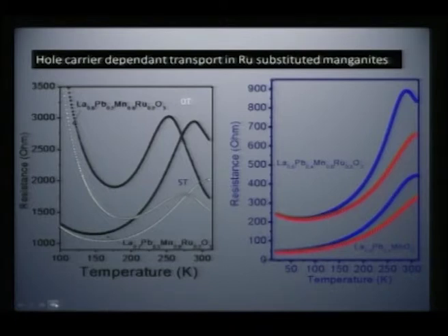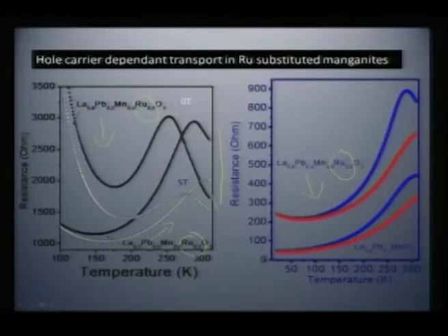We can also try to verify that by keeping ruthenium 0.2 constant in all these cases, and we can try to vary the lead concentration, 0.2 in this case, 0.3 in this case, 0.4 in this case. You can clearly see there is a change in the metal insulator transition, but nevertheless they are still ferromagnetic and they are showing a metal insulator transition. And if you also look at the fall of resistance, say for 0.2 and 0.3, there is a huge fall in the resistance for both these compositions. So what is happening is there is an unusual correlation between manganese and ruthenium, which we should take note of, and we can try to see what exactly is responsible.